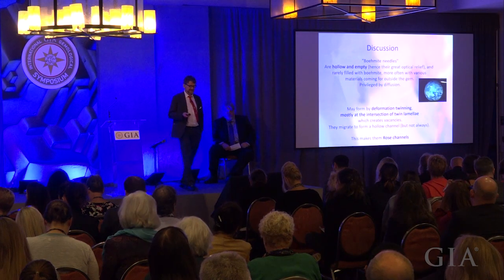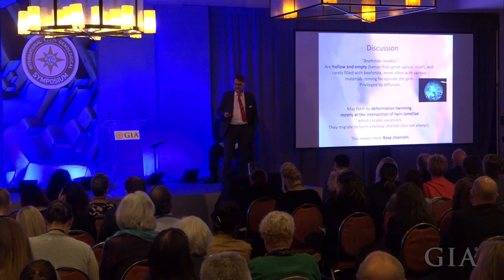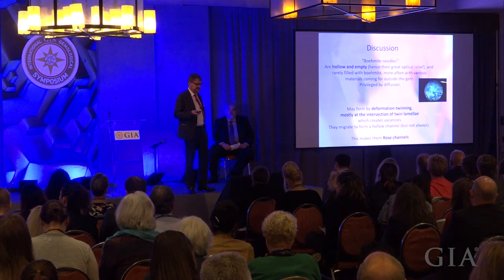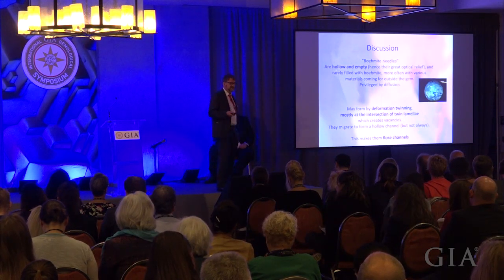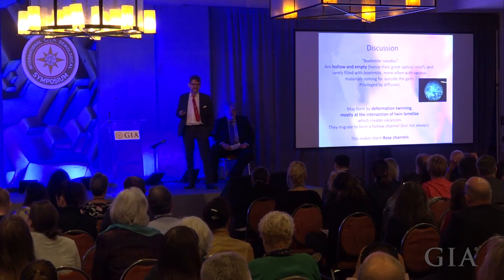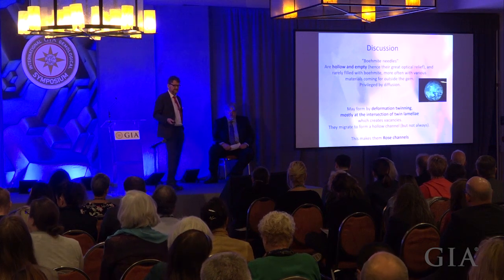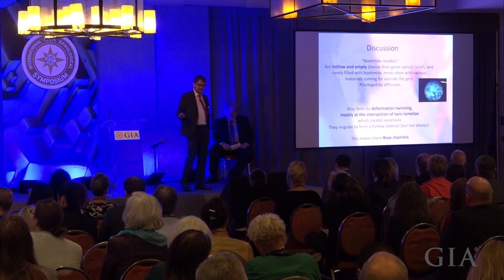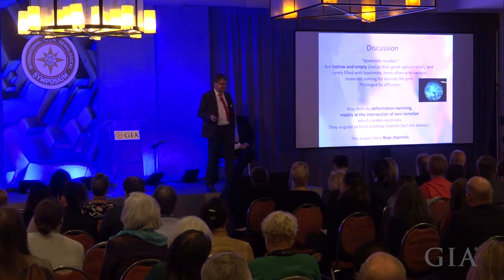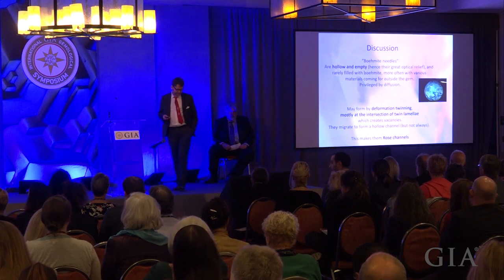Because if you think about it, if there was Boehmite in there, Boehmite is about 1.65 refractive index. Corundum is about 1.75. That's 0.1 contrast in index of refraction. They wouldn't be that visible. They are extremely visible. But the fact that they're hollow matches that extremely well, because then you have a contrast between 1, roughly the refractive index of air, and 1.75. That's 0.75 refractive index contrast. Then that perfectly explains why they are so visible even when they're tiny.